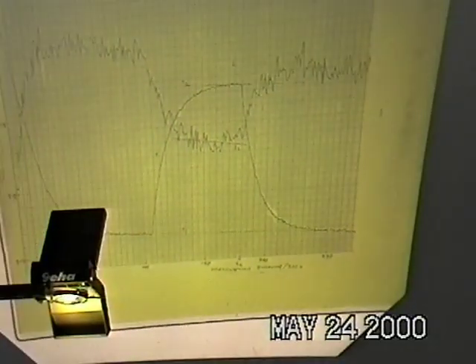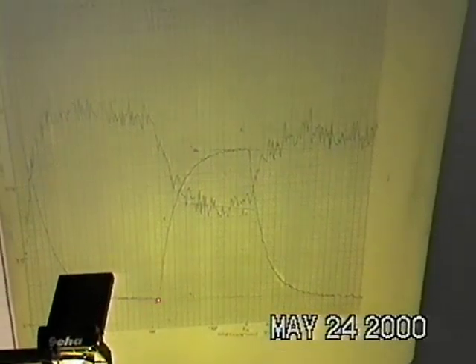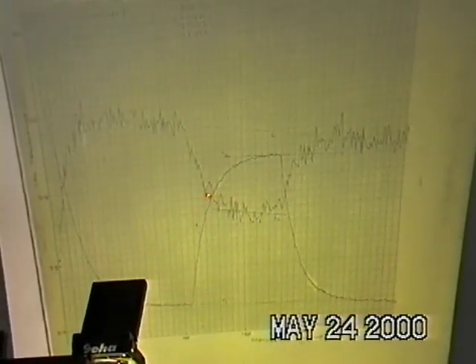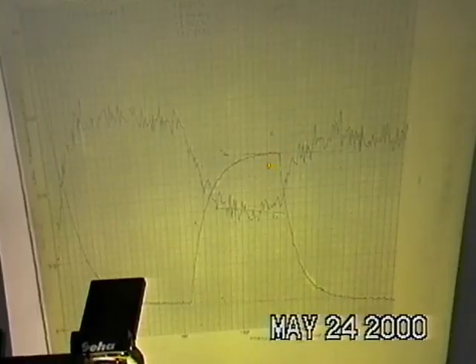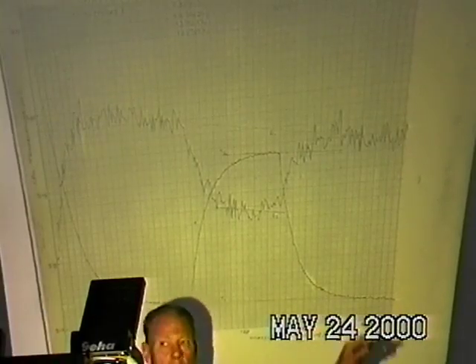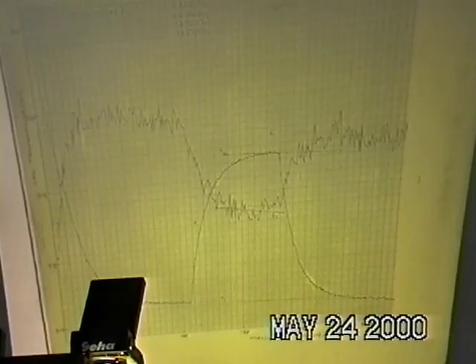This is data I plotted out of another heating cycle. We turn on the calibration heater. Here it does level out better because there's no positive feedback, or very little in this case. And you see it relaxes back. I do a straight line here, and it relaxes back to about the same baseline. So in this case, it looks like there was not a serious problem, perhaps, with positive feedback.